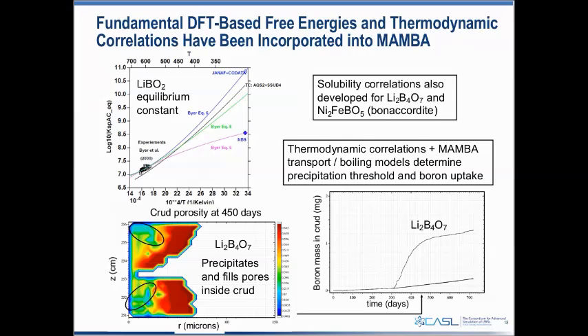This slide shows, for example, the fundamental DFT-based free energies and thermodynamic correlations we've been developing, and these have been incorporated into MAMBA. The top left figure shows an equilibrium constant for LiBO2. We've also developed other solubility correlations for lithium tetraborate as well as bonaccordite, and these models are in MAMBA. The bottom left figure shows the Crud porosity at 450 days in a simulation.